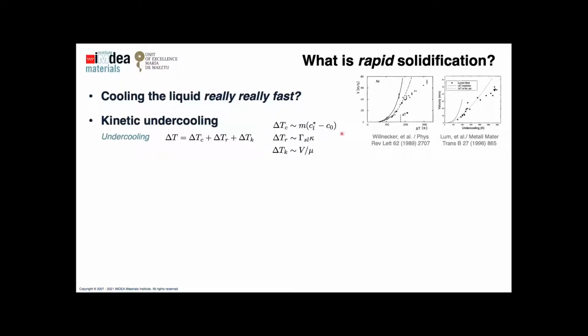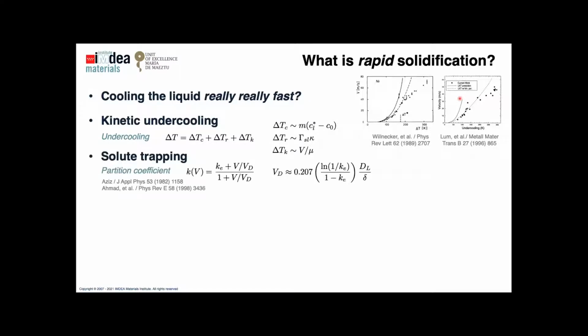And how do we know that exists? Well, we look at experiments, for instance, on deeply undercooled droplets in levitation, and we see that in order to fix the theory versus experiment, we need to include the contribution of this kinetic coefficient. Another effect that also has been mentioned by Charles-André is solute trapping. When your solidus and liquidus line are getting together, they merge somewhat, your partition coefficient tends to 1.